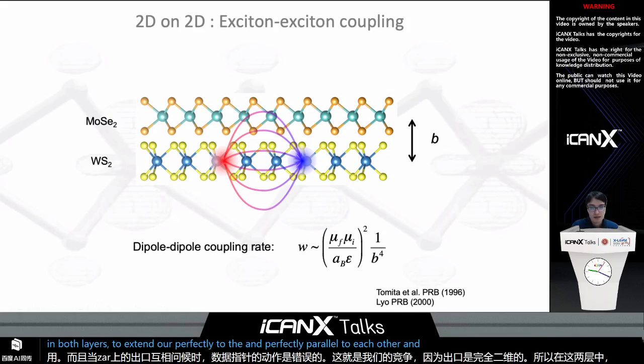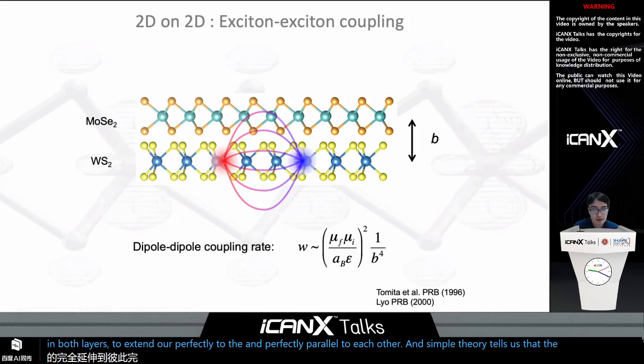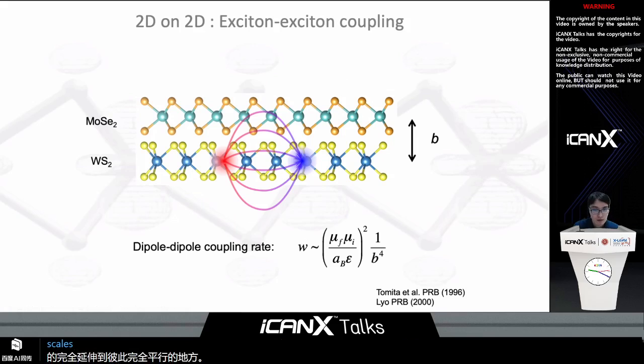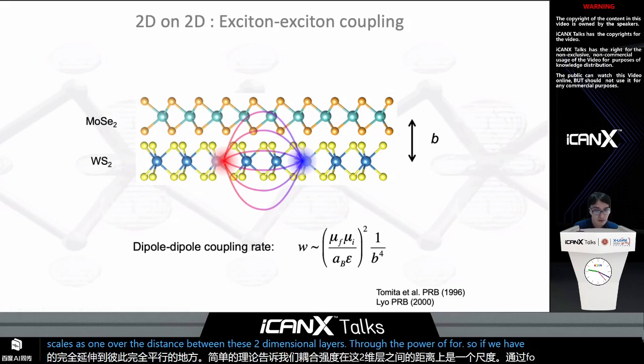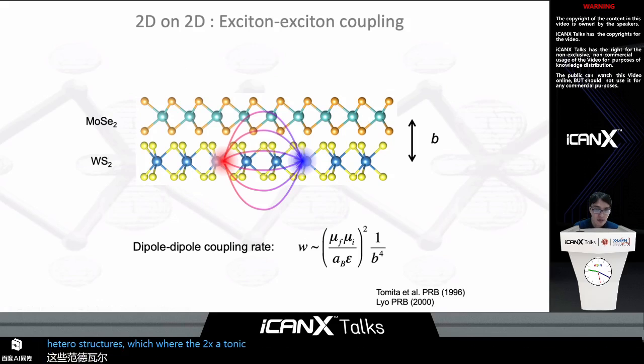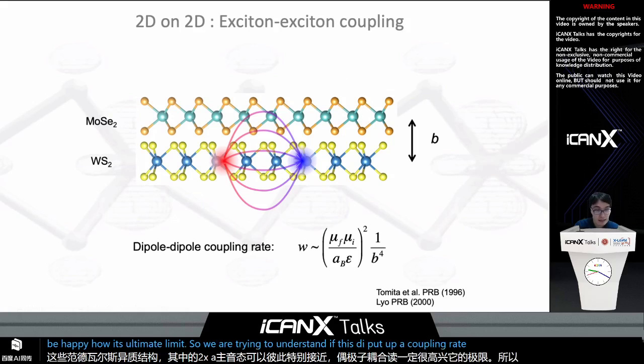Well, simple theory tells us that the coupling strength scales as 1 over the distance between these two-dimensional layers to the power of 4. So if we have these van der Waals heterostructures, where the two excitonic states can be spatially as close as possible to each other, the dipole-dipole coupling rate must be at its ultimate limit. So we were curious to understand if this dipole-dipole coupling rate is indeed at its ultimate limit.